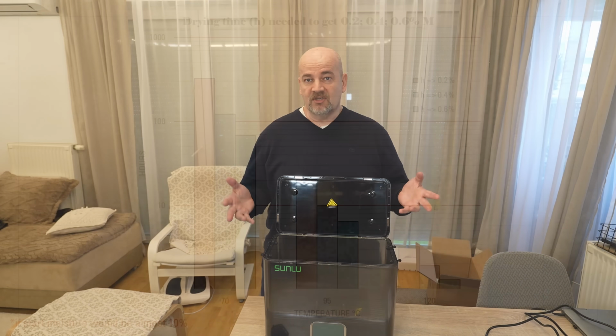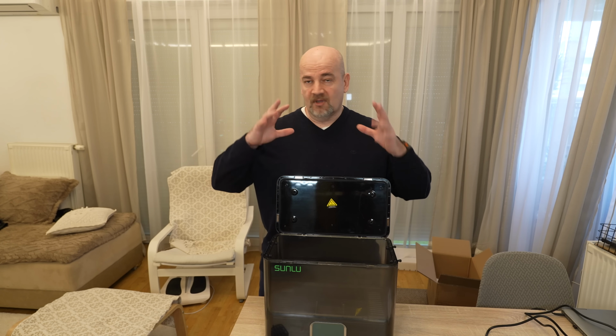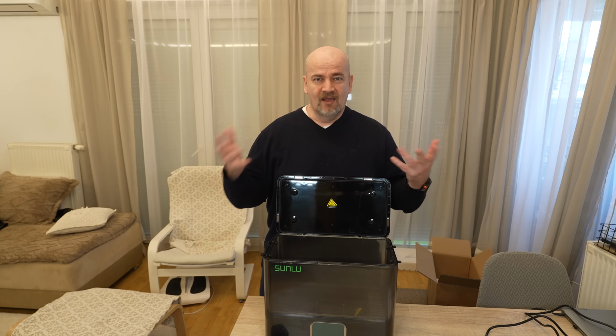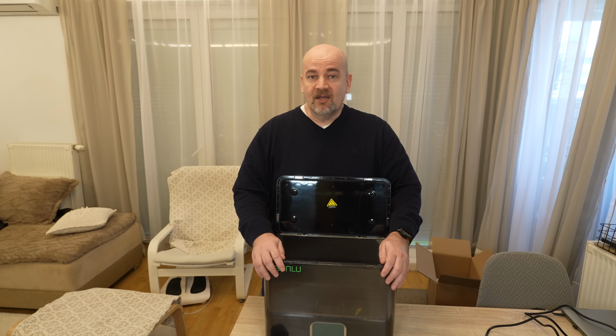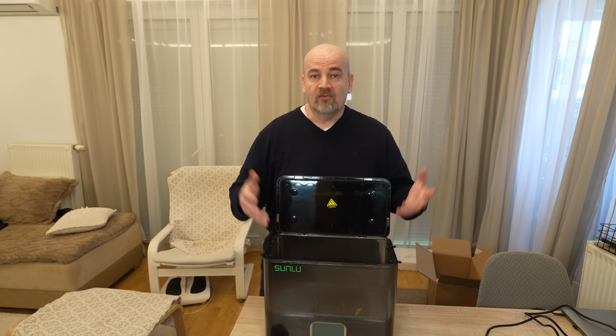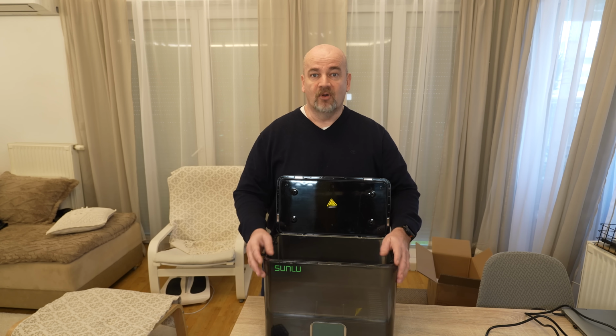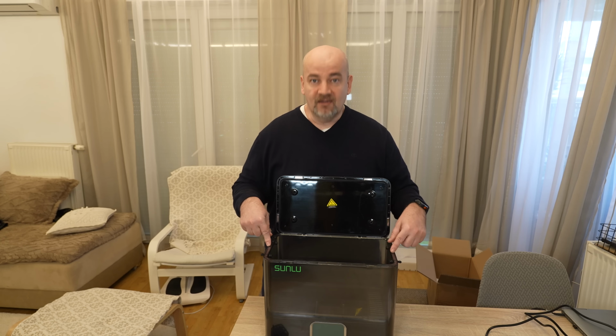And the conclusion was, if we want to dry the nylon at 70 degrees Celsius, let's say which was stored outside, I don't know, maybe a month, in our case it was in the water, and it absorbs a lot of moisture. In that case, we need more than a week to dry it completely to the state which we can use for the printing. At 90 degrees Celsius, I don't remember correctly, but it was, let's say, 1 day or something like that. And at 120 degrees Celsius, this can be done in 3 or 4 hours. So the temperature is extremely important, and we can reduce this drying time significantly by drying at 120 degrees Celsius.